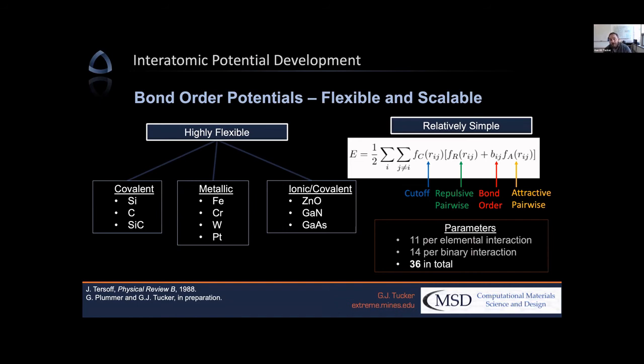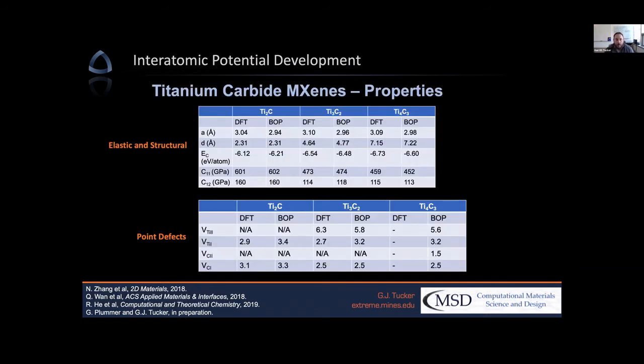We have to numerically optimize to a set of target data, and in our case, that target data is both experimental data and a lot of DFT data as well. When we develop this potential and optimize it, we have to test it. So we took both the elastic and structural properties and various properties of point defects. Shown here are three different stoichiometries of titanium carbide MXenes, the 2.1, the 3.2, and the 4.3, comparing published DFT values and the bond order potential calculated values. As you can see, across the board we get very nice agreement in all three chemistries, and down through the table looking at a bunch of different elastic and structural properties: the elastic constants, the lattice parameters, cohesive energy, and then down at the bottom, various point defect sites within the MXenes.